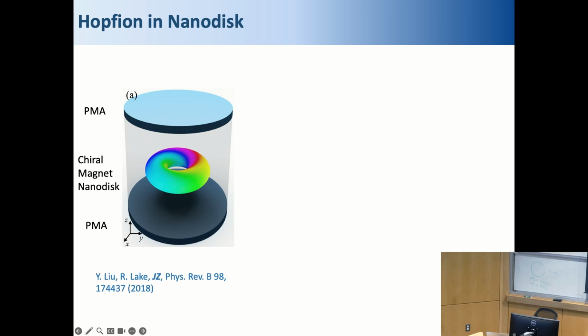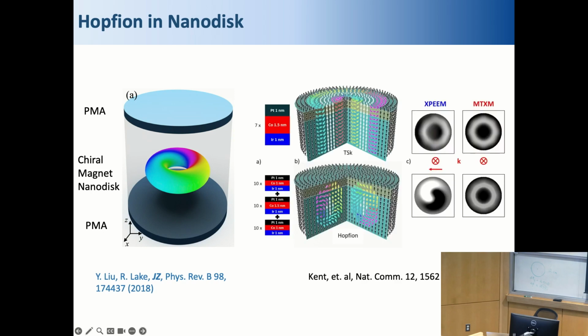I just showed that an iron germanium nanodisk can host a target skyrmion. But once this nanodisk is sandwiched in between two spin polarized layers, as a result, there will be a hopfion inside. And there are some X-ray measurements on this kind of setting, but they choose a different realization of the skyrmions inside. They use magnetic multilayers, but the idea is the same, and they confirm that there is a hopfion configuration inside.